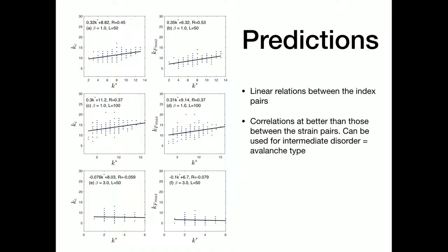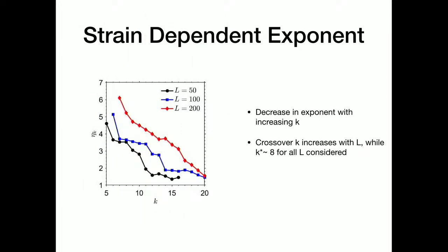the highest, higher betas have very poor correlation, which is expected because nucleation type is even harder to predict, the more brittle behavior compared to the avalanche. We also reproduce the strain-dependent exponents in terms of it going from higher to lower levels.